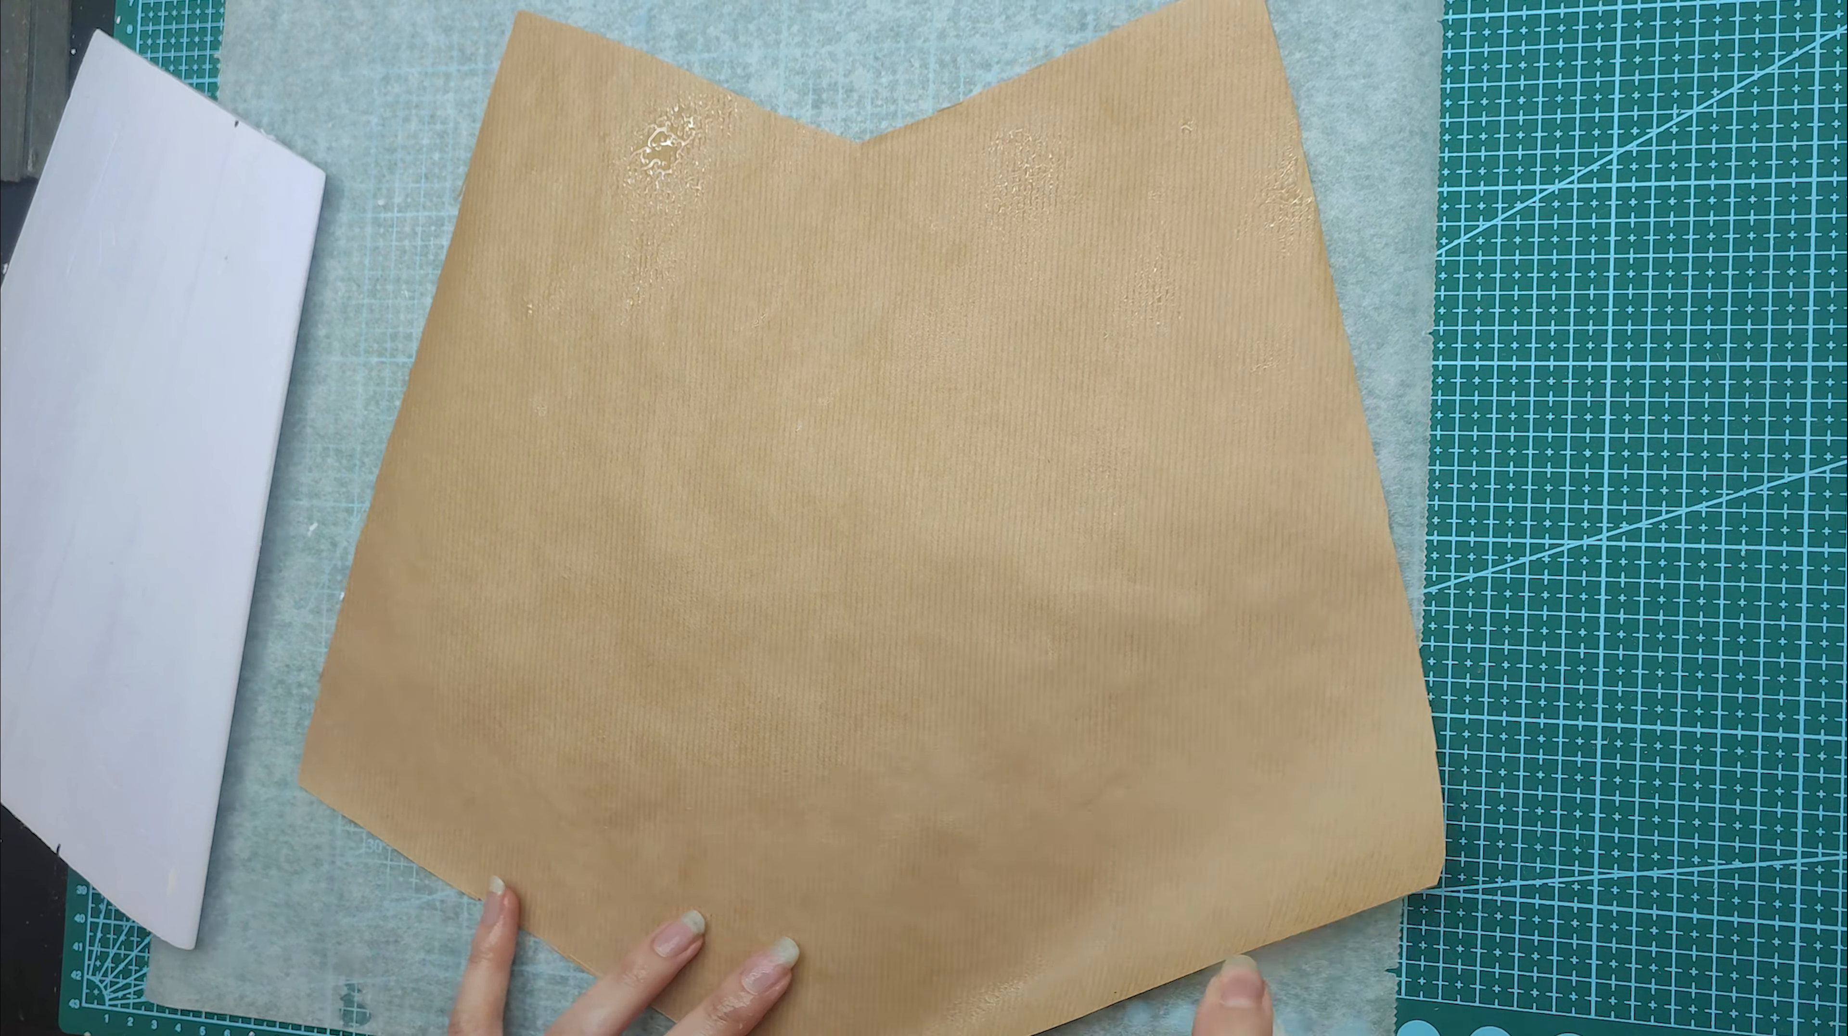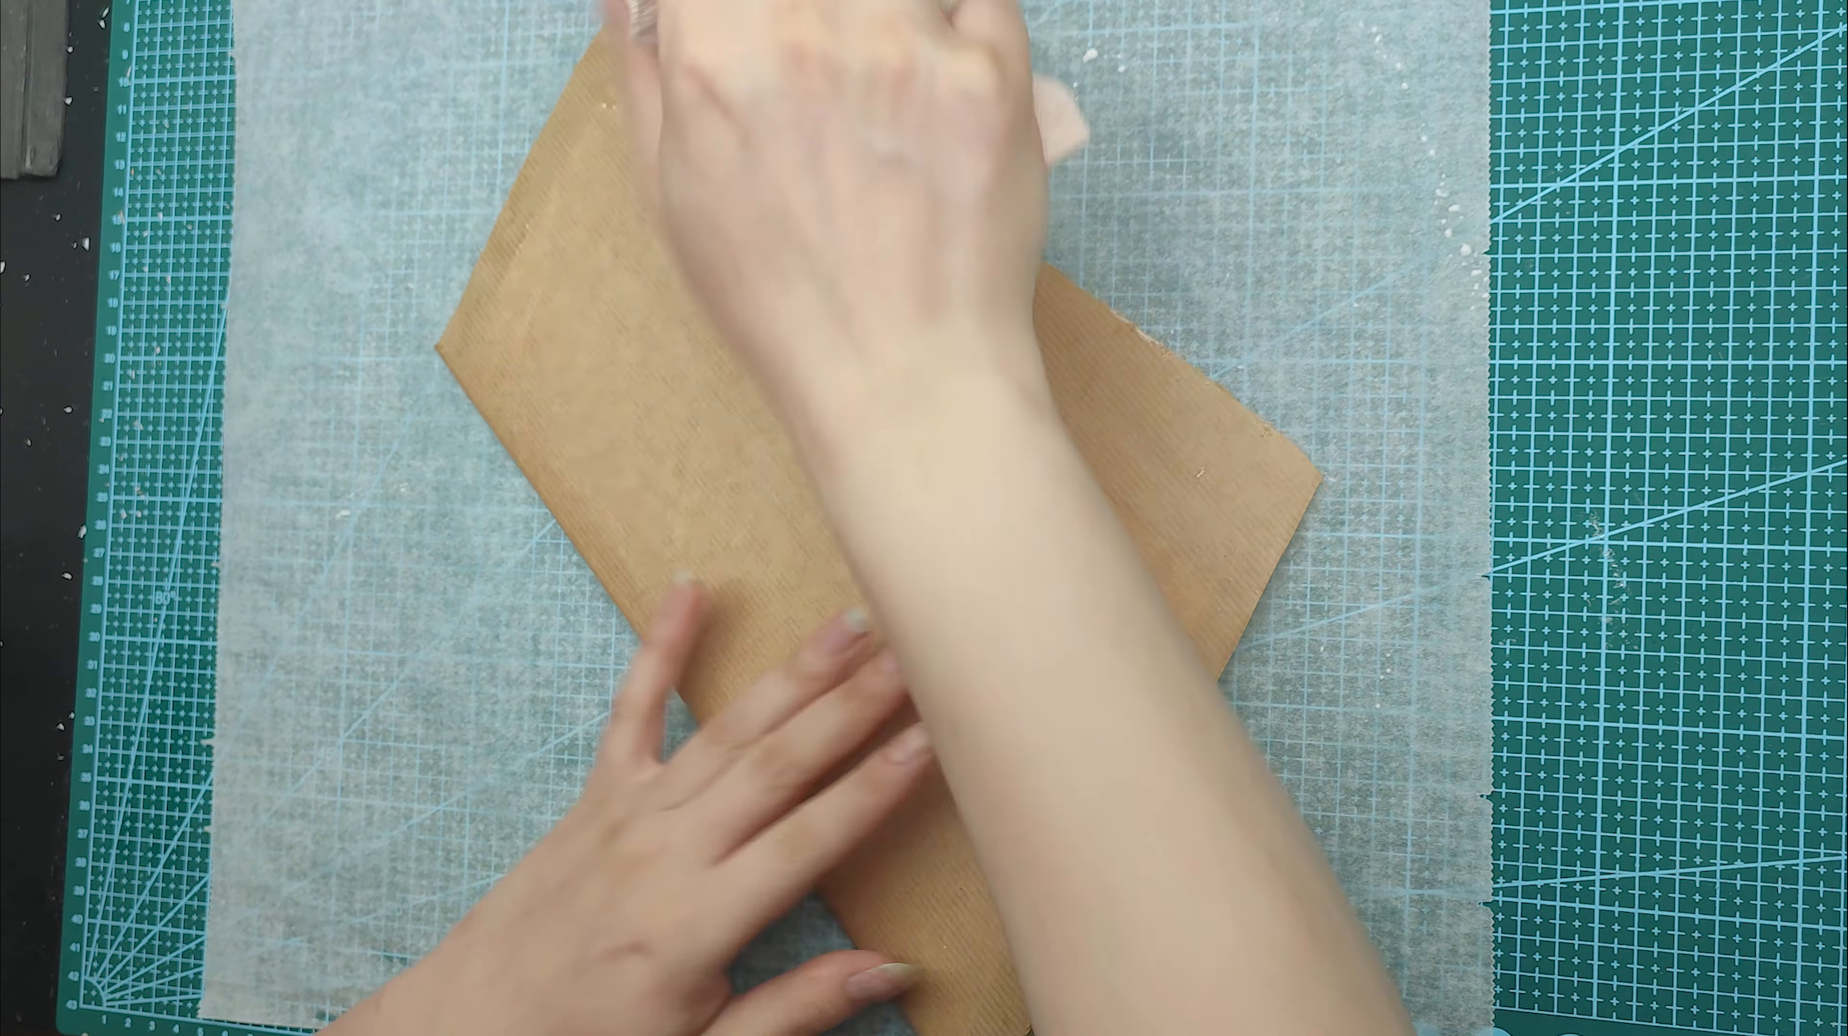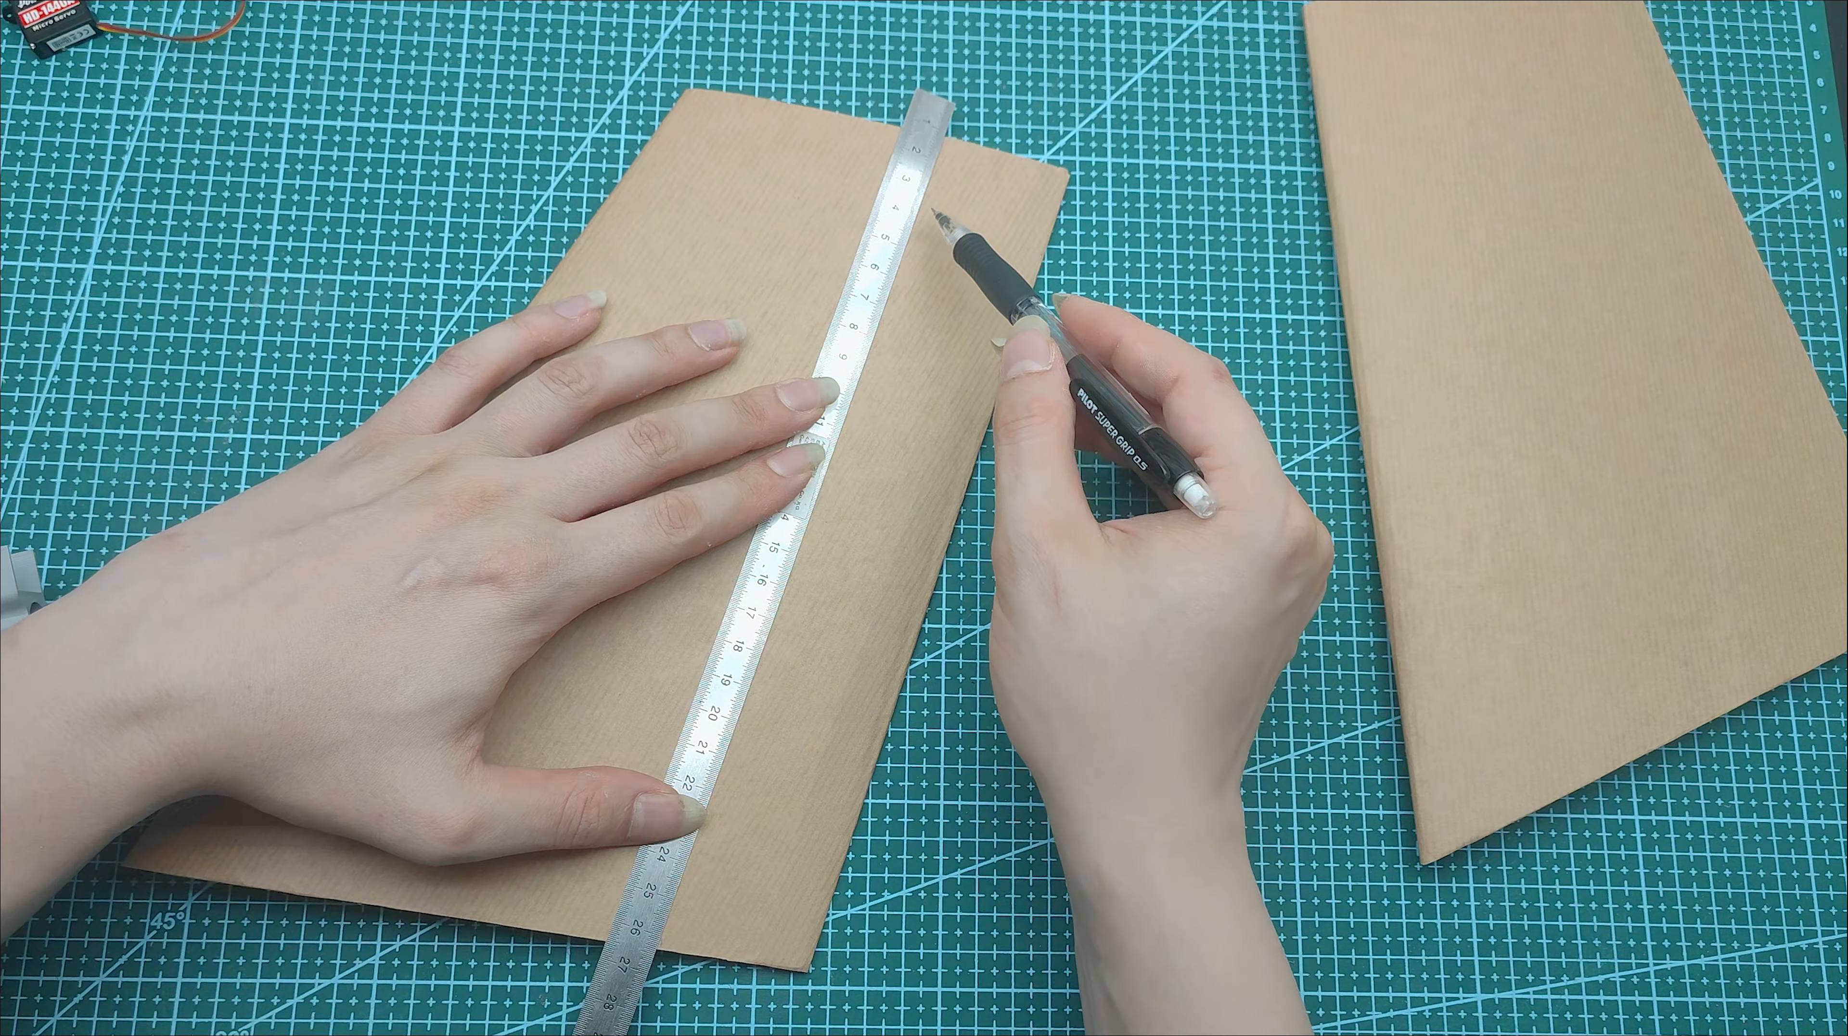I just don't feel comfortable with servo and wire being stuck to the wing for good. Spray the paper with some water and let it soak. Wipe all the water excess and apply glue on the foam. Smooth the paper out and next fold the overlap over the trailing edge to make it more rigid. Use the table to fold it over. The same process for the leading edge and the other side. You can fold over the trailing edge for a second time to make it even stronger as the foam itself is really weak there. I also recommend spraying the paper with some water to relieve strain while the paper dries out to prevent twisting. Consider air humidity and temperature. The glue and paper dry at different rates. When it's dry, the paper gives the foam significant strength and low extra weight. The surface is so great. Really smooth and precise.